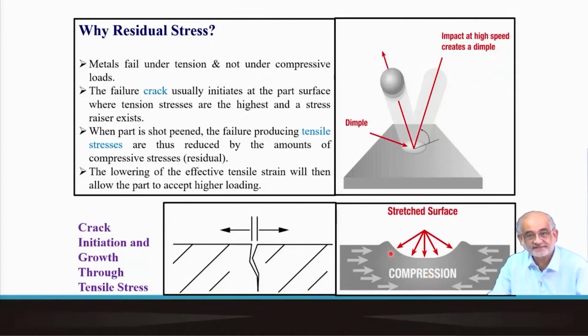So due to the elastic nature of the deformation at that point, all the grains in the neighboring region will try to push the material back into the deformed region. And as a result, we develop stresses with directions as shown by these arrows, which are directed towards each other.